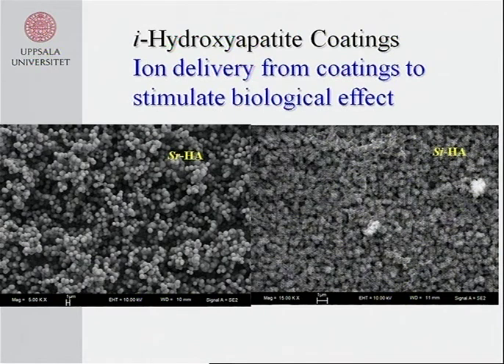What I would like you to pay attention to is the completely different morphologies that you can create just by tailoring the composition of the hydroxyapatites. In this case, and I will show you later, these are spheres. They're perfect spheres, and they are hollow. For some reason, which we don't know exactly why, they form these hollow spheres at the moment. And the silicon HA forms like a bundle of very, very small crystals.